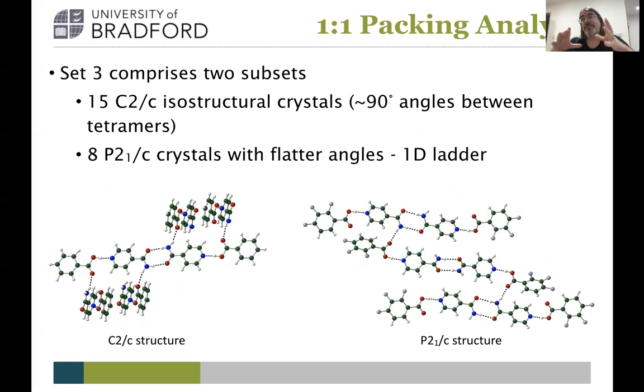Set 3, however, once we've got that 90-degree rotation and hydrogen bonding throughout the lattice, very much fixes the total packing. So 15 of the systems are completely isostructural, and they're all the ones that have them at 90-degree angles to the original tetramer. So if we can get that strong hydrogen bonding throughout the crystal, we start restricting the potential crystal packing directionality, and we can start then controlling the crystal structure, and then hopefully changes in physical properties are directly related to the chemical changes rather than the changes in the crystal packing.